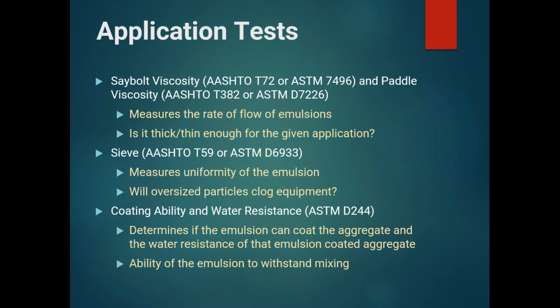Another application test is sieve, and Andrew mentioned that one. This is where we're measuring the uniformity of the emulsion by looking for oversized particles. So are there a lot of oversized particles that may clog your equipment or cause you problems when applying this emulsion? And then coating ability and water resistance.